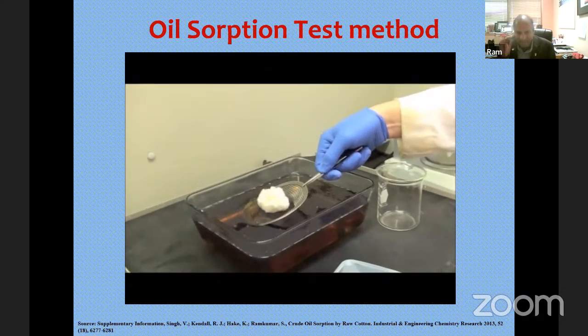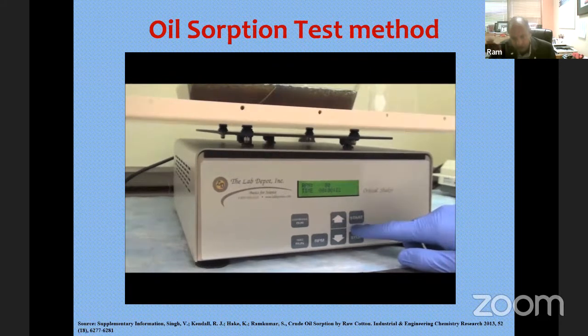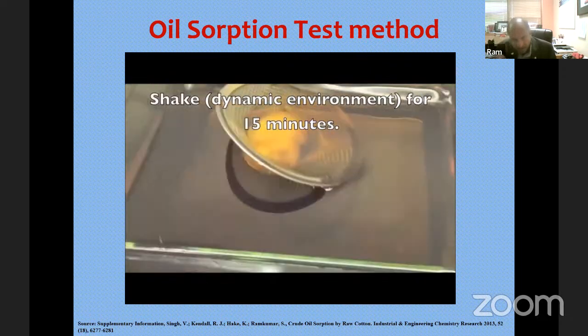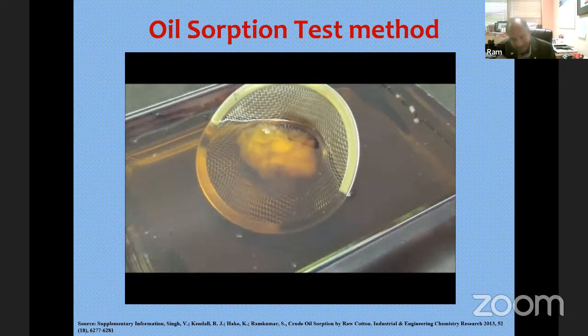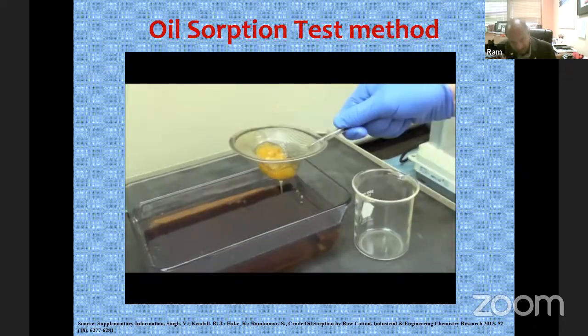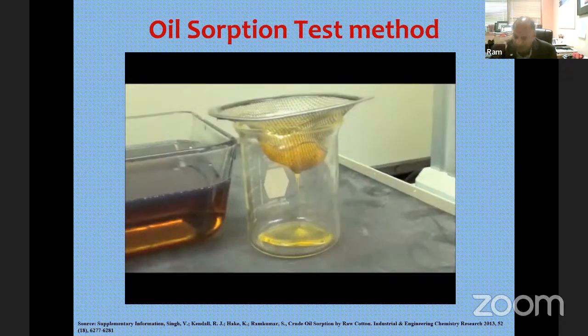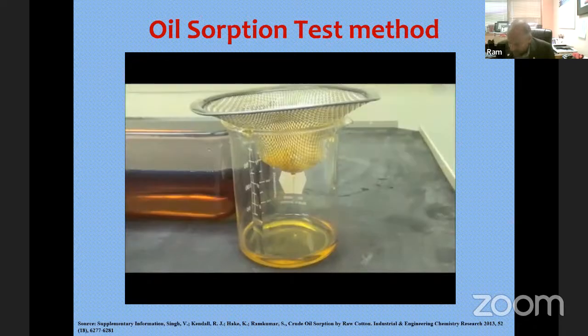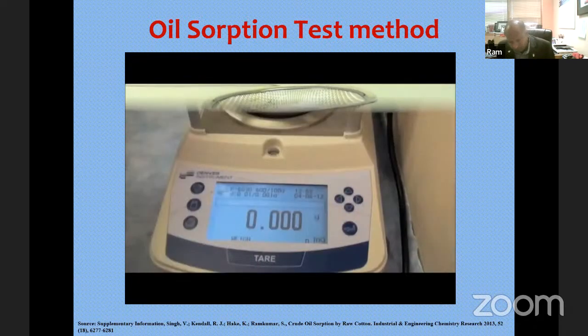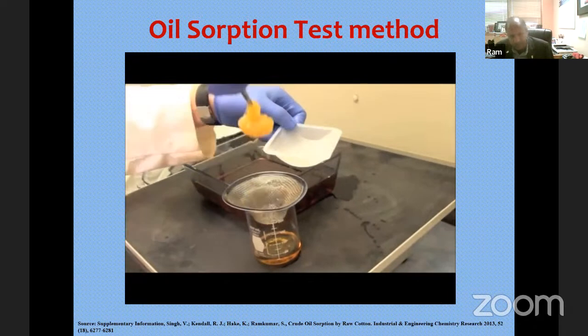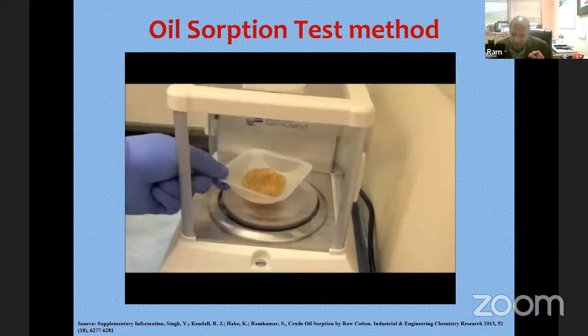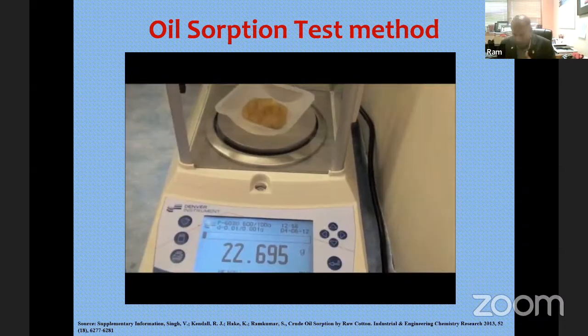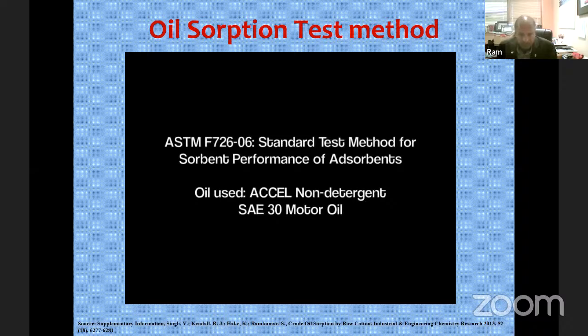You will see this. Instantaneously, it will soak up oil. You can see that it is not sinking. It instantaneously soaks up the oil and it will hold up to 30 to 50 grams. Each gram of cotton will hold anywhere from 30 to 50 grams. That is, it will hold 30 to 50 times of its weight. So I'm going to show you results. We have proven this.